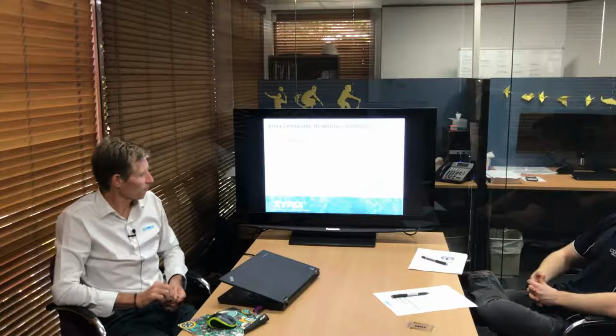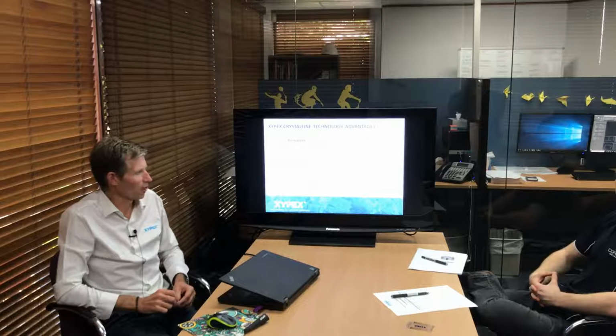Similar to the increased early and later age strength, we do exhibit improvements in lower drying shrinkage, which assists, once again, with the finish of the concrete. Highly resistant to aggressive chemicals. Now, consistent chemical range with pH 3 to 11, and then you can handle splash or intermittent 2 and 12.